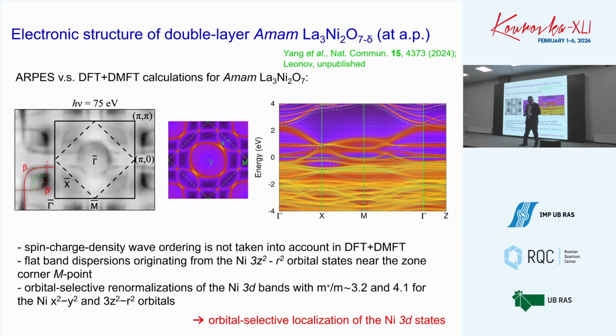But I would say that some transport experiments claim that the system is close to an insulating state. But people measured the Fermi surface here, some kind of renormalizations, etc. It coincides quite nicely with our results, if we neglect this density wave state, more or less a good agreement. Although this experiment was done, I think, at relatively low temperature, possibly very close to this density wave phase.